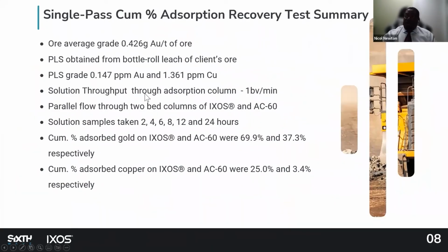Results show that with the single pass, we're pulling about 70% of the gold and 37.3% of gold respectively, 70 and then 37% respectively for the IXOS and then activated carbon for gold, and then 25 and 3% for the copper.